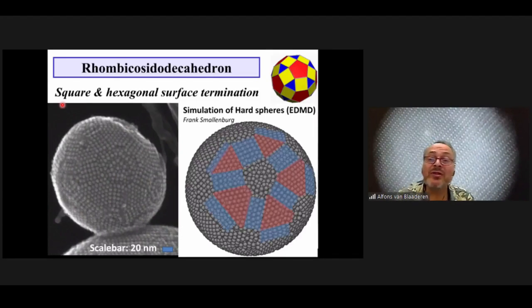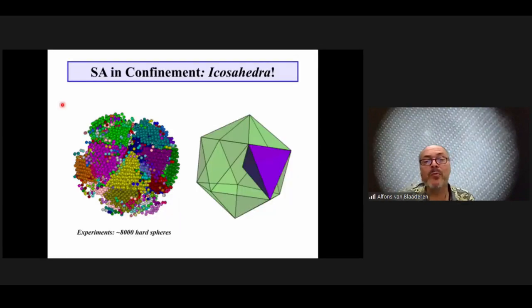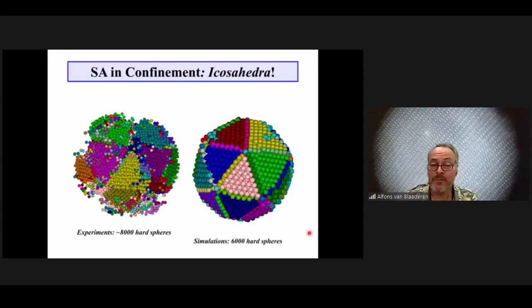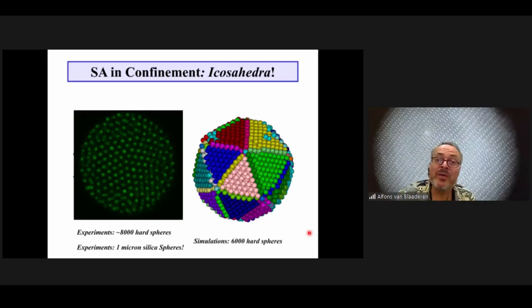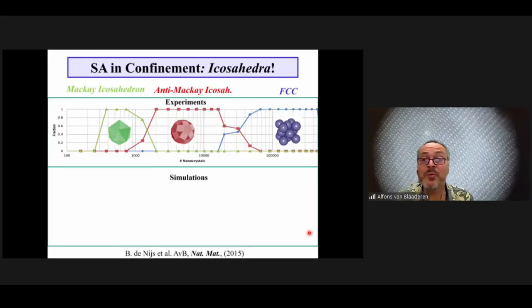So this is a computer simulation, one of the earliest done by Frank Smallenburg. Like 6 years ago, we couldn't find all the nanoparticle positions, but now we have advanced and we can easily get all the coordinates of all the nanoparticles. But even with this 80% of the particles found, we clearly saw the icosahedral structuring of the particles inside, which was exactly what we also found in the computer simulations. And as I mentioned, we also found it for micron-sized spheres, but then the drying has to be very slow.